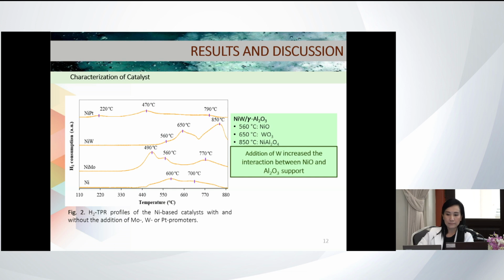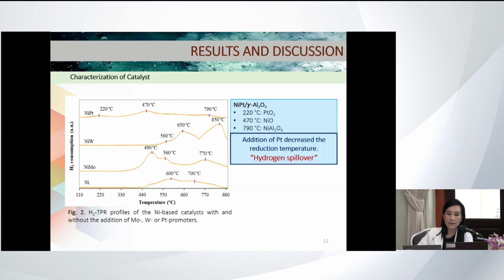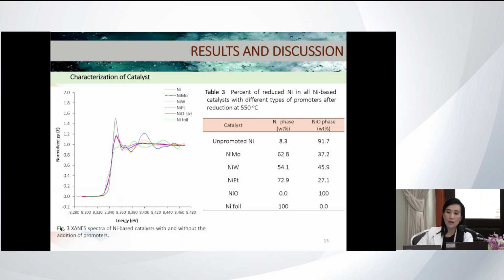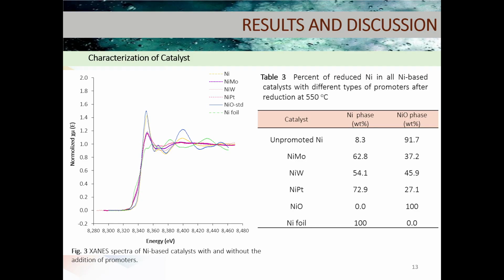For the nickel platinum, it shows the lower reduction temperature because of the effect of hydrogen spillover, in that the hydrogen adsorbed on the surface of the platinum can be transferred to the nickel oxide phase easily. To confirm the hydrogen TPR, we use X-ray absorption near-edge spectroscopy to find the amount of nickel active phase, and you can see that the nickel oxide, nickel molybdenum, nickel tungsten, and nickel platinum show a high amount of the nickel active phase.